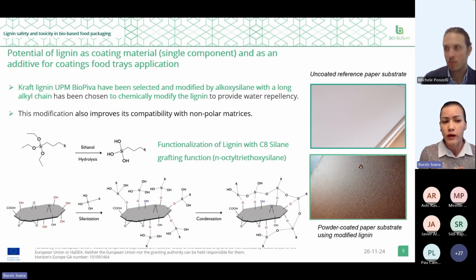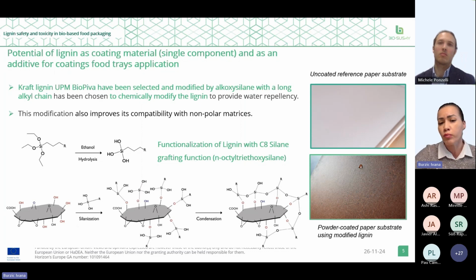So what has been done at the early beginning of the project, we use the kraft lignin from UPM. BioPIVA is the grade, because it has to be modified, and it was being modified by our partner from France, Sychemia, by alkoxysilane with long alkyl chains to chemically modify it to provide water repellency.